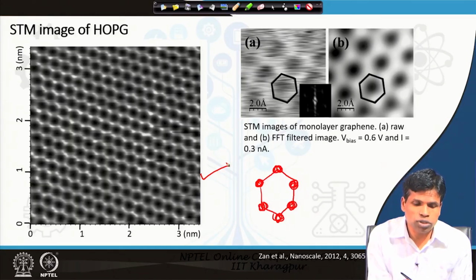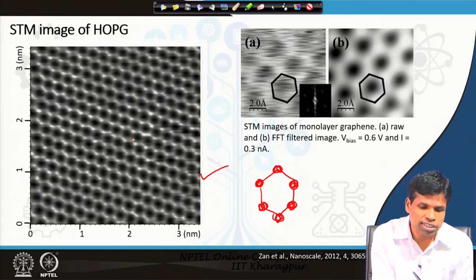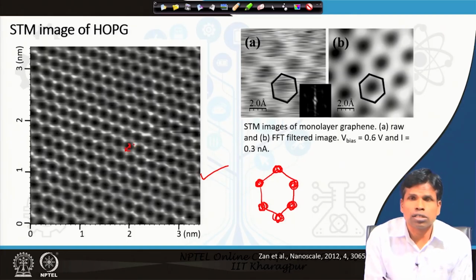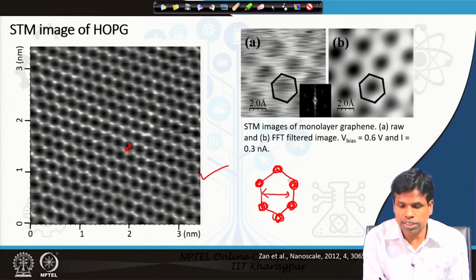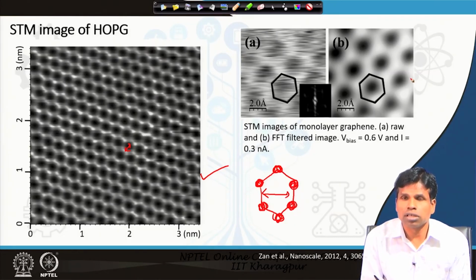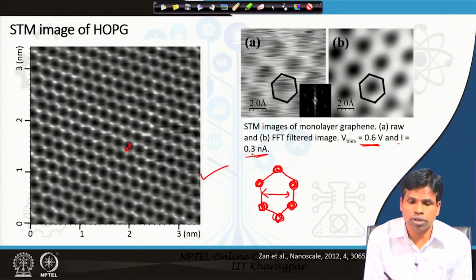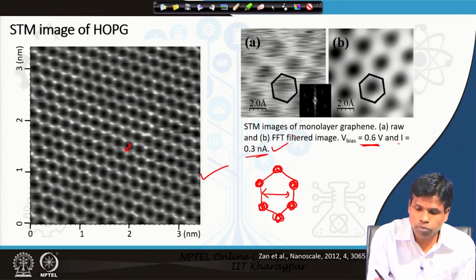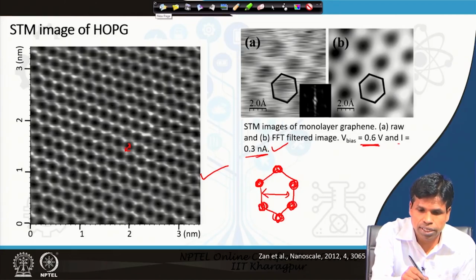HOPG. And as you see now, you can actually measure the distance between carbon atoms and the hexagon diameter, or all kinds of measurements at the atomic level. And this is a monolayer graphene showing the hexagons with a bias voltage, as you see, of 0.6 volt and a current of 0.3 nanoampere. At a constant current of 0.3 nanoampere, it is measured in the graphene case.